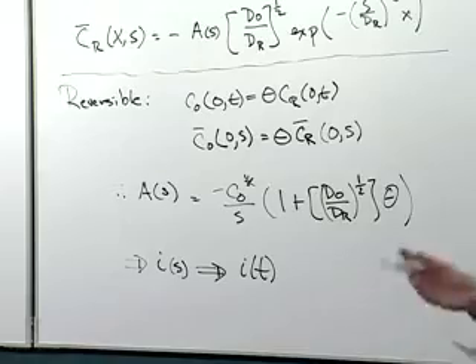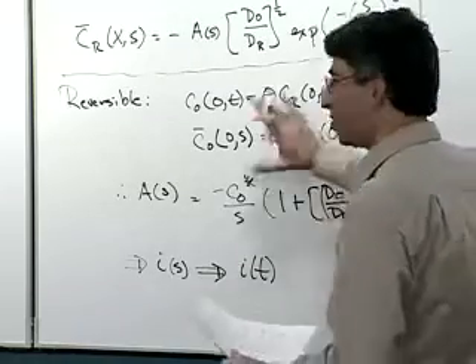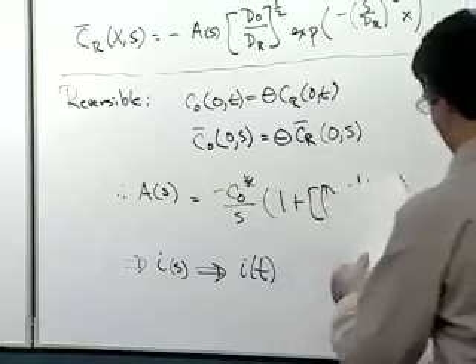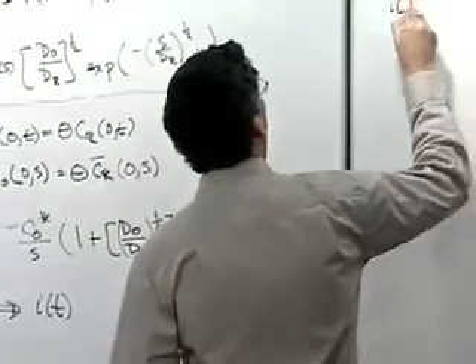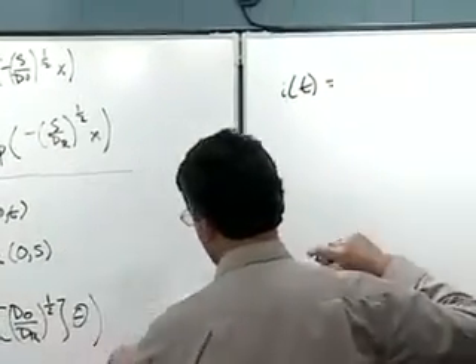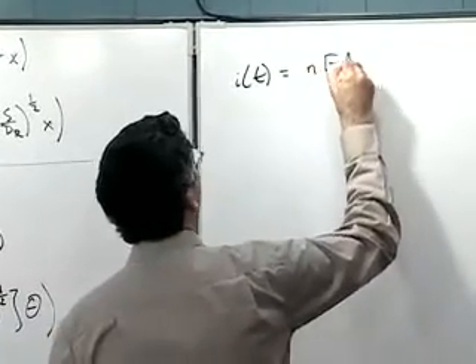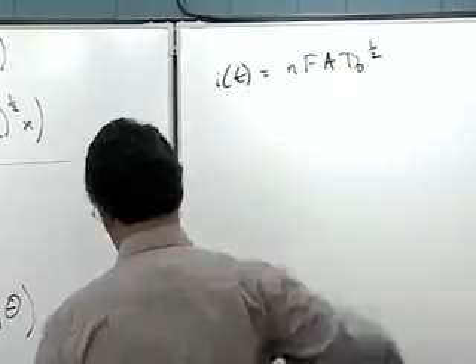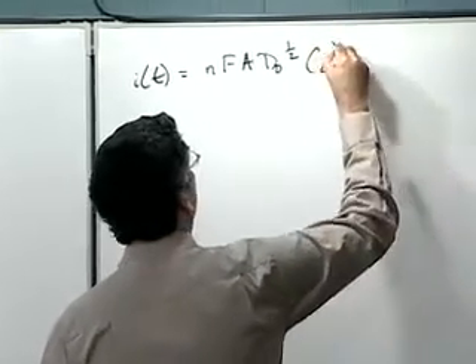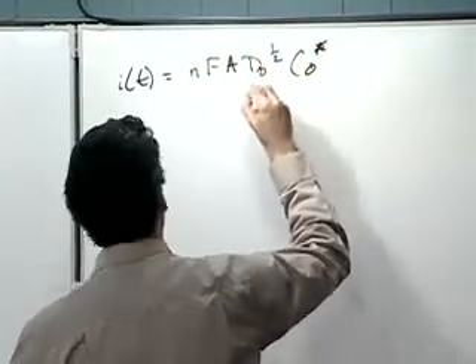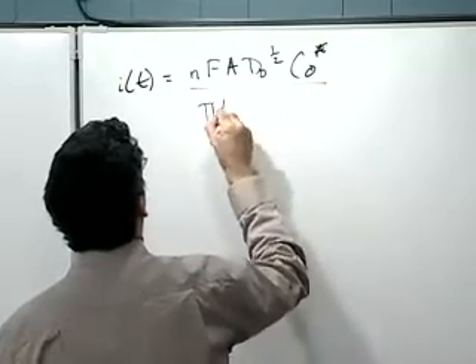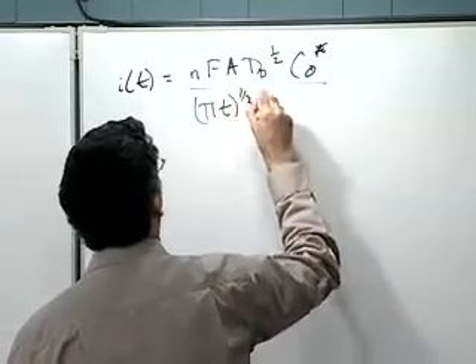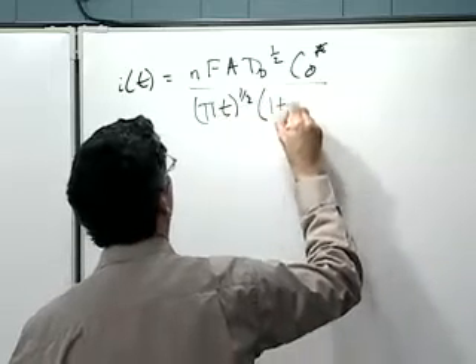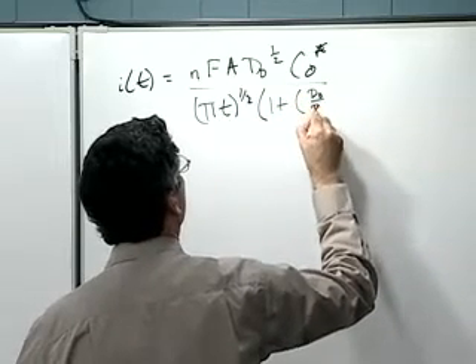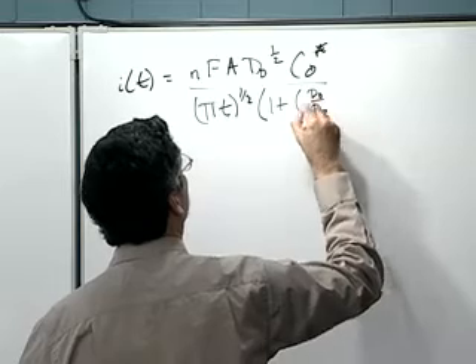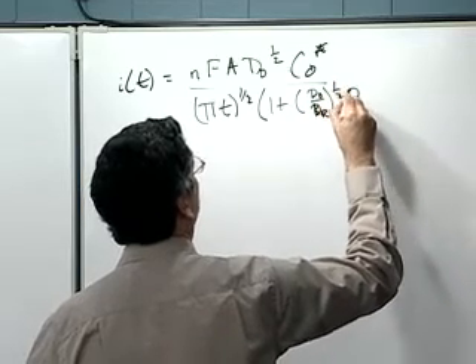And so speeding up this whole operation, if you do all those steps, and this is just algebra that I'm talking about right here, then we come up with the fact that the current as a function of time is equal to n f a, diffusion coefficient to the 1/2 power, bulk concentration of oxidized species, divided by pi times time to the 1/2, times 1 plus this ratio of diffusion coefficients times theta.